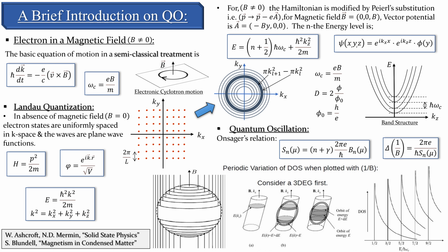Here is a Landau tube, and for some energy height kz, the energy is Ekz. In the second picture, there are no orbits in the range E to E plus dE energy shell that occupy an extremal position. The same construction is done in the third picture, except that here the energy is now that of an extremal orbit, and for that we get a peak in the density of states plot. Here the figure shows a typical density of states plot for a fixed magnetic field. For the change in energy for different Landau tubes, we get this situation, and it falls like the one dimensional density of states.